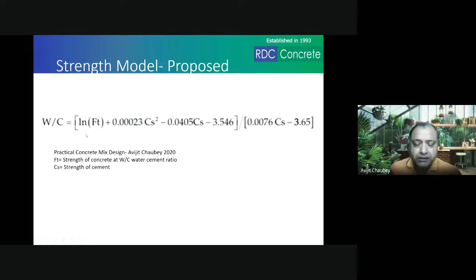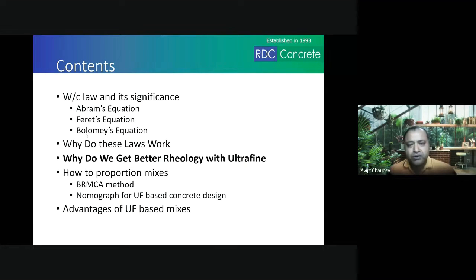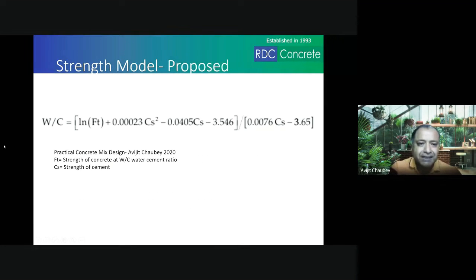So this equation is what I have developed based on my years of study, and it works well, and it works even for, let us say, 3 day strength. So if you want a 3 day strength, let us say you put a water cement ratio of 0.5, you again at 3 days, whatever strength you get, you put that strength over here. So CS would be the strength of cement in 3 days. So if you want a different strength for the same set of materials in 3 days, you just plug in that strength for 3 days and plug in the strength for cement for 3 days, and you will get the water cement ratio. So this is how this equation works.